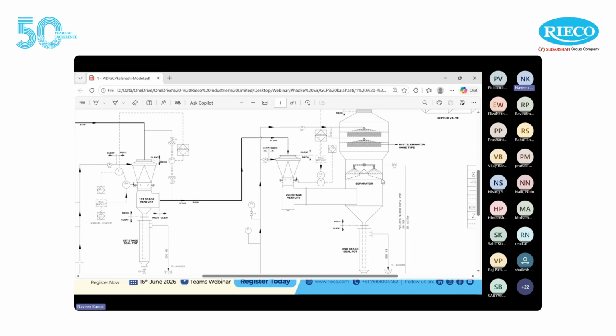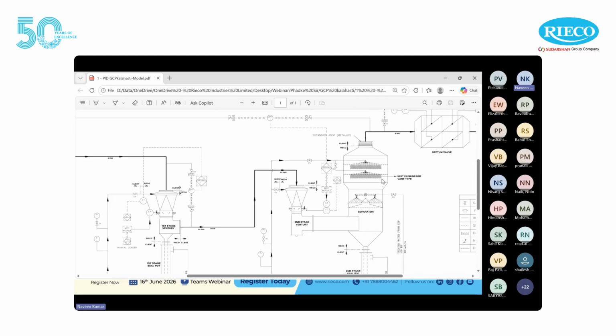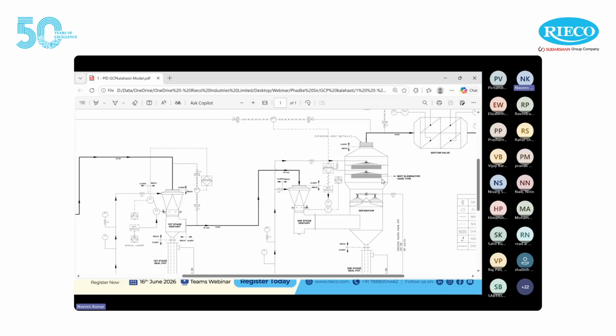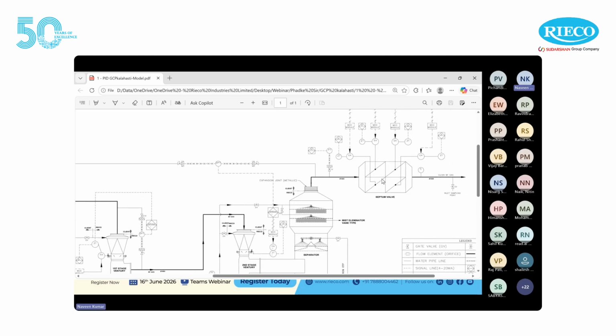The gases which are cleaned of all the fine powder are then taken to the separator, which is a cyclonic separator, from where the gases emerge through a mist eliminator where the vapors are removed. In the end, we have a seal valve which helps to reach the desired pressure suitable for further processing in the hot blast stoves. And so the cleaned gas is delivered for usage downstream. So that is a typical gas cleaning plant.